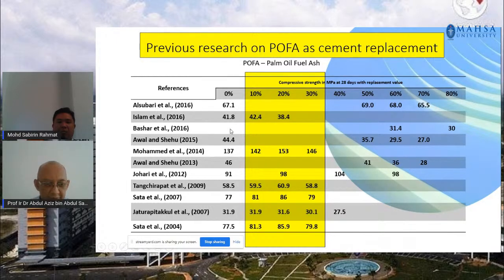The same goes for Islam et al. 2016. They've also done reasonably good research work in terms of palm oil fuel ash as cement replacement, and the results are quite reasonable. Other than that, we can also see that researchers have gone beyond 30% of cement replacement. They have gone up to 50%, 60, 70, and even 80% of cement replacement of POFA. And the results are quite okay.